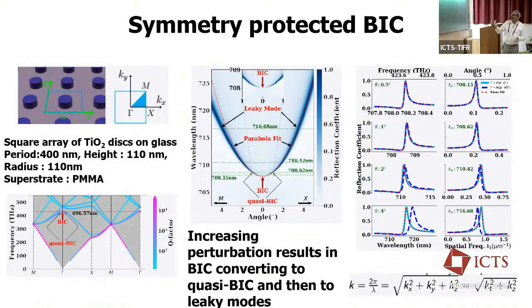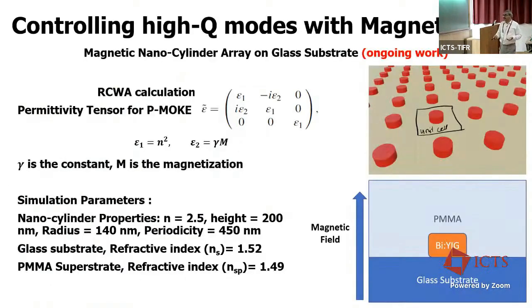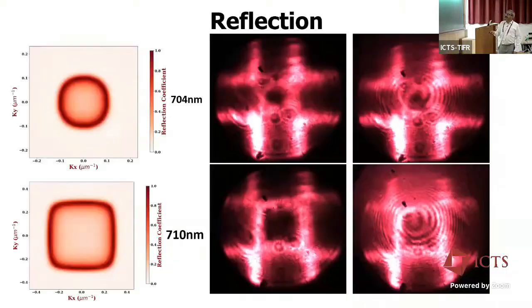Right? These have asymmetric line shapes. And right now what we're looking at is controlling these high Q modes with magnetic field. So we made this bismuth doped yttrium iron garnet. This is a ferromagnetic material. So we made these discs with ferromagnetic materials, and we are looking at controlling the emission of single photons in the orbital angular momentum states.